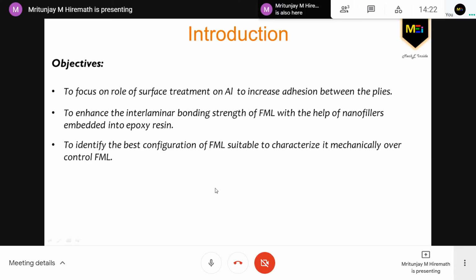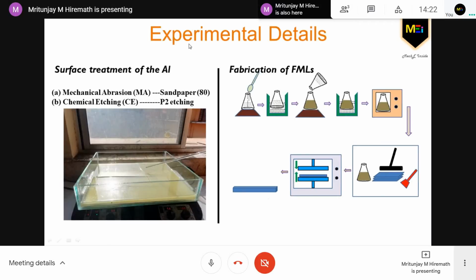The third is to identify the best configuration of FML which can be suitable to characterize it mechanically over the control FML. These objectives were fulfilled while doing the research in our institute, in our Matless Lab, and were successfully achieved. To carry out these objectives, the experimental details include surface treatment of the aluminium first. The first surface treatment was mechanically abrading the aluminium surface with sandpaper of 80 grit size. The second was etching it chemically with aerospace standard P2 etching. This is how the P2 etching process was carried out.